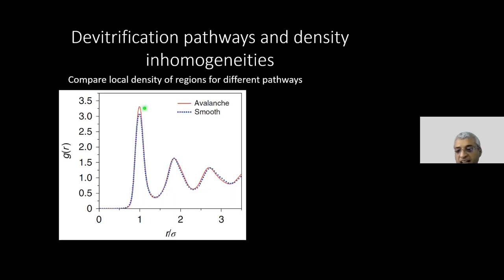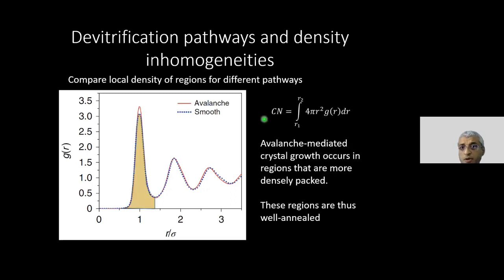And the fact that I have a taller peak matters, because if I integrate the area under the curve, what I get is the number of particles in my nearest neighbor shell. The taller peak means that in regions where an avalanche process went through, the particles are better packed. So in an experimental laboratory prepared glass sample, because I have not done any special procedure to create either a poorly annealed or a well annealed glass, I am going to see regions of density inhomogeneities, and these density inhomogeneities are going to give me two different routes.